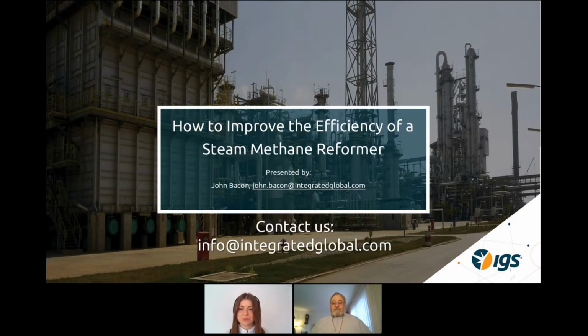Do you have any reference benefits on the tube life? Tube life, like I said, we don't put coating on the tubes, so we don't affect the tube life. In refinery-fired heaters, where they use a steel alloy tube, not a nickel chrome tube, we do put coatings on those and stop oxidation altogether. And yes, that will increase tube life. If the coating lasts for 10 years in a refinery-fired heater, then we probably extend the tube life by 10 years. But in steam methane reformers, we don't apply coatings to the tubes, so that's not an issue.